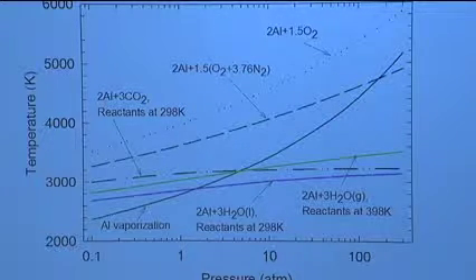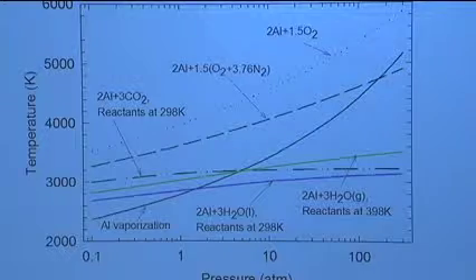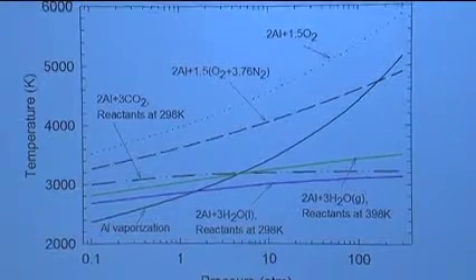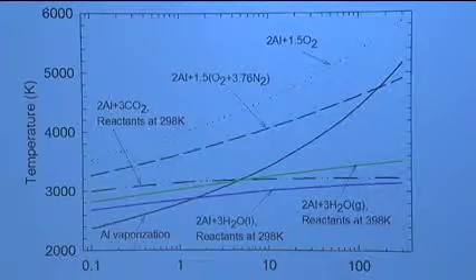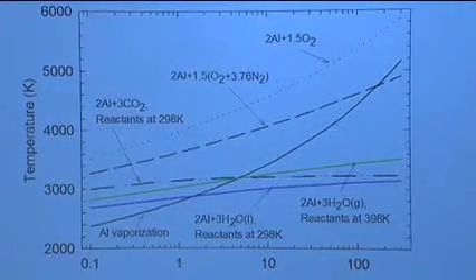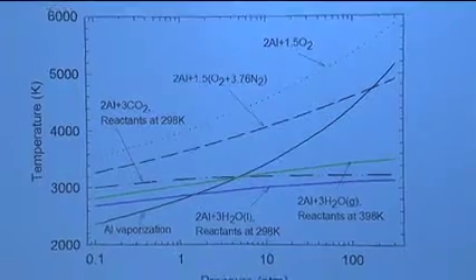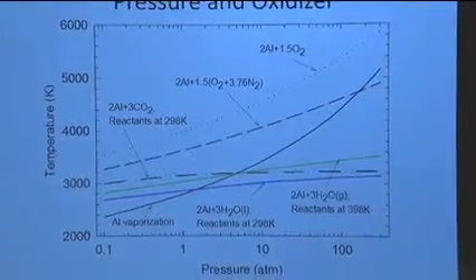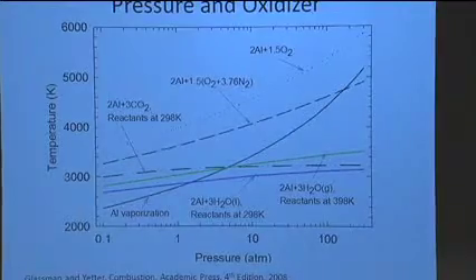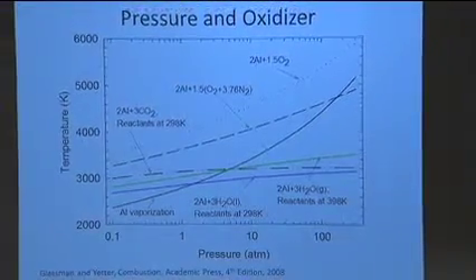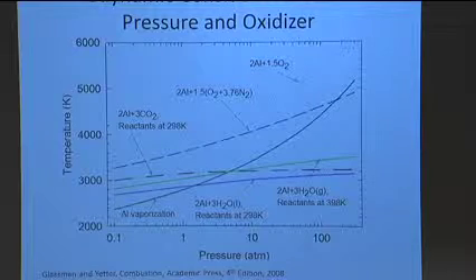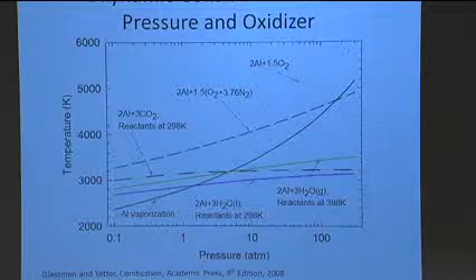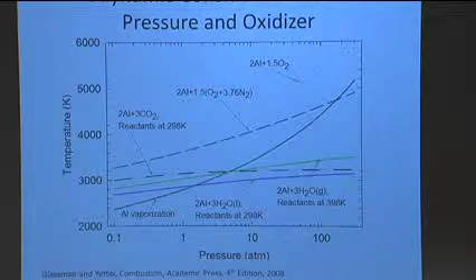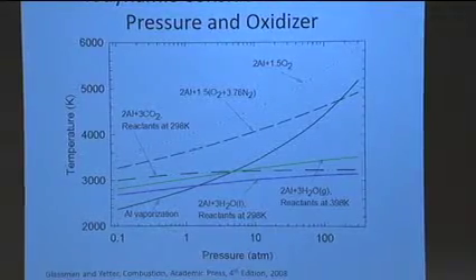Okay, if I look at one atmosphere here, I want to really pull out two curves. The first curve here is essentially aluminum reacting with a simulated air, or air here, so oxygen and nitrogen. And what I'll find then is at 1 atmosphere, the flame temperature is about 3600 or 3700 Kelvin, okay? So that's the reaction temperature. The other line I want you to look at is this line. This is the vaporization temperature here. So if I look at the temperature at which aluminum is going to vaporize, it's about 2700 Kelvin at 1 atmosphere. So the flame temperature is higher than the vaporization temperature.